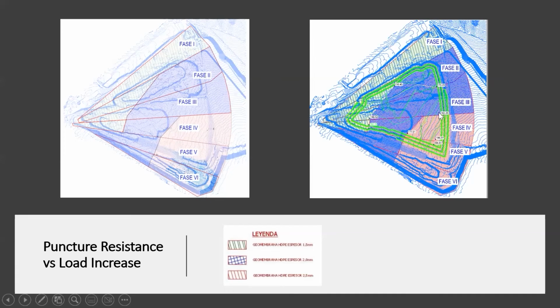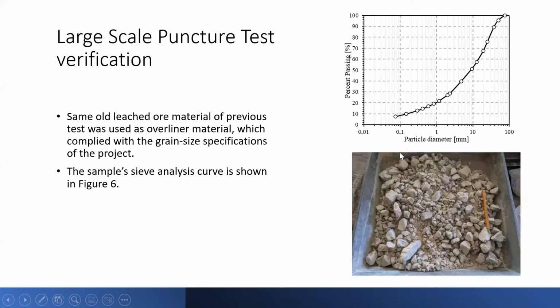And over this was projected the additional layers of leach ore to put in there. With the stability analysis, the maximum areas that were possible to do it without affecting the global stability were also determined, along with the maximum heights for different areas and the different thicknesses here, and we performed the different tests for these different stages. So the same leach ore material of the previous study was used, just taking in consideration the maximum 2 inches as a maximum particle size.